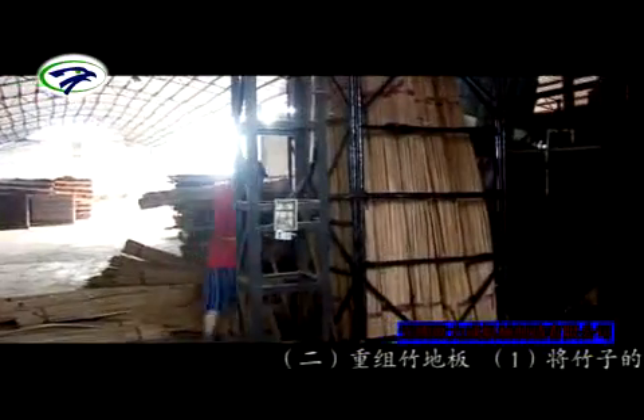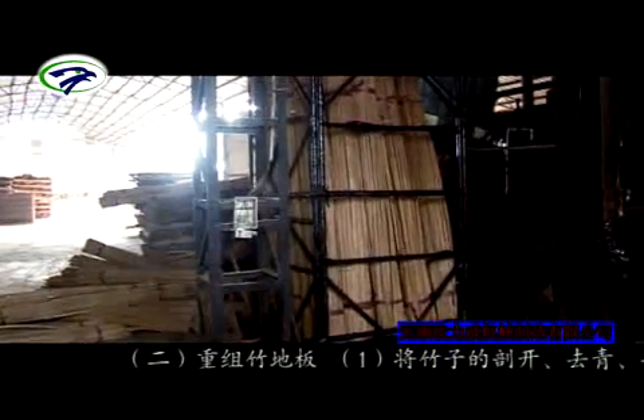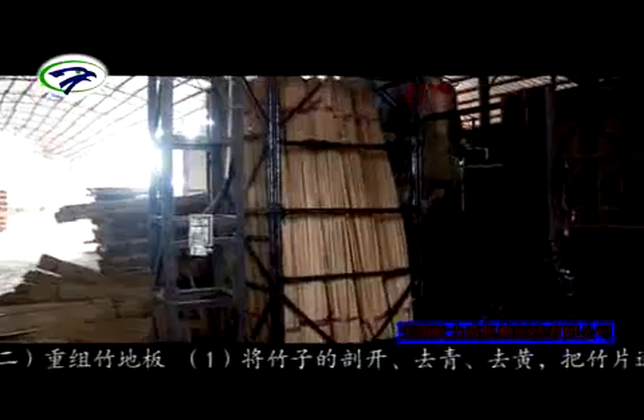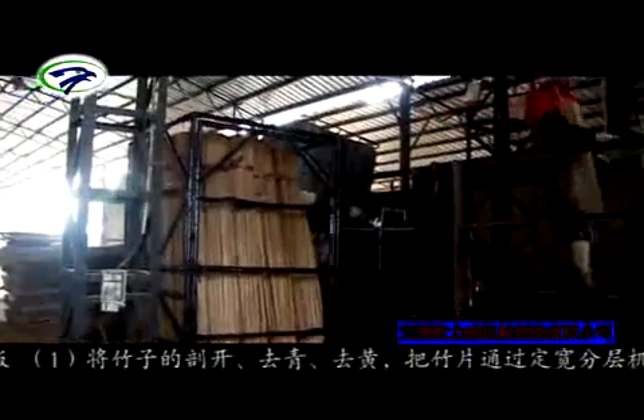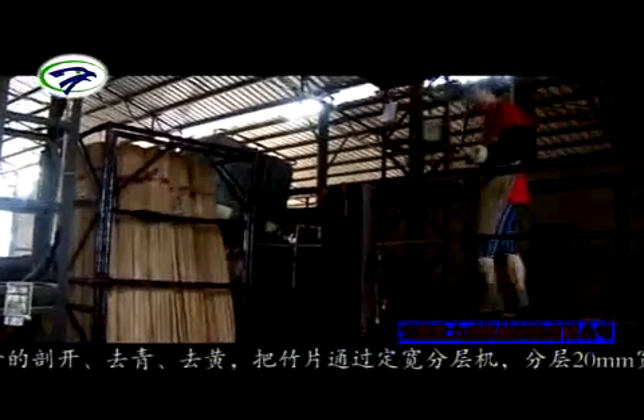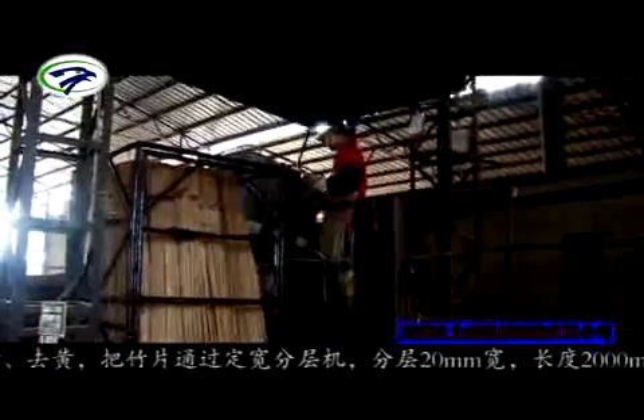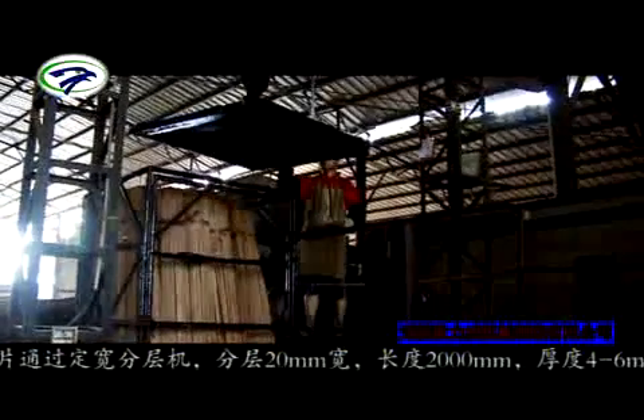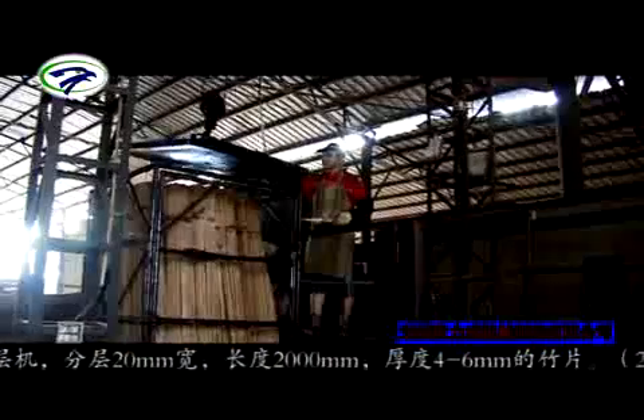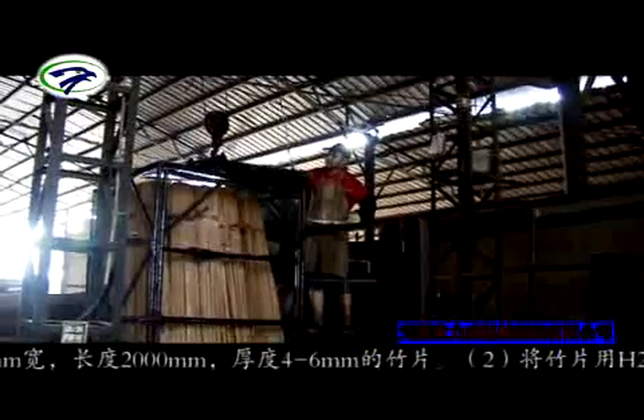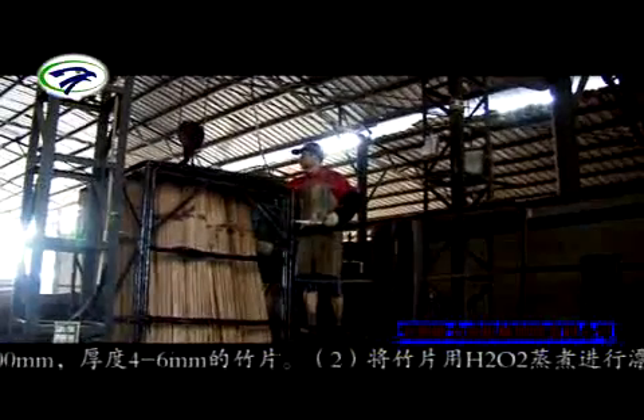B. Recombinant bamboo flooring. 1. Cut open the bamboo and remove the green and the yellow parts. Delaminate the bamboo slices through the width-set delamination machine into bamboo strips 20 mm width, 2000 mm length, 4 to 6 mm thickness.